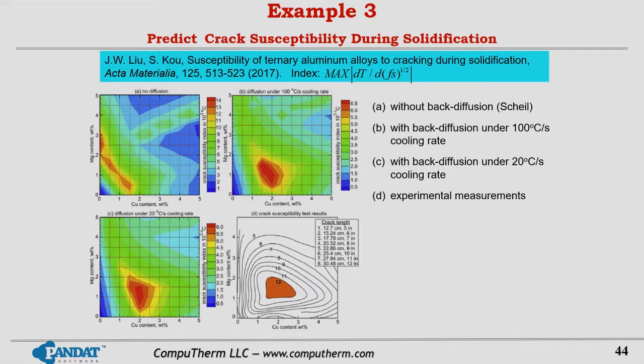In this model we do not consider back diffusion. As you can see, the map of the cracking region, the orange region, is kind of off from the experimental data. However, if we consider back diffusion, for example figures B and C both consider back diffusion but with different cooling rates, both of them predict the red area, the composition area that's most vulnerable for cracking during solidification.